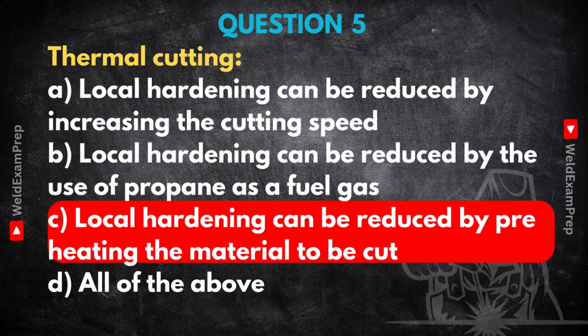Now, quickly on the others. Increasing cutting speed, A, might actually increase hardening sometimes by reducing total heat input, but still having rapid cooling right at the edge. It's not a reliable way to reduce hardening. And using propane, B, versus, say, acetylene, different fuel gases have different flame characteristics. But changing the fuel gas isn't the primary method aimed at controlling the metallurgical transformation caused by the cooling rate. Preheating directly addresses the cooling rate issue. Got it. So preheat is the targeted solution for mitigating that local hardening. It really links back to understanding the material science, the heat transfer. It's all connected. It absolutely is. Welding, cutting, material behavior, it's all intertwined.